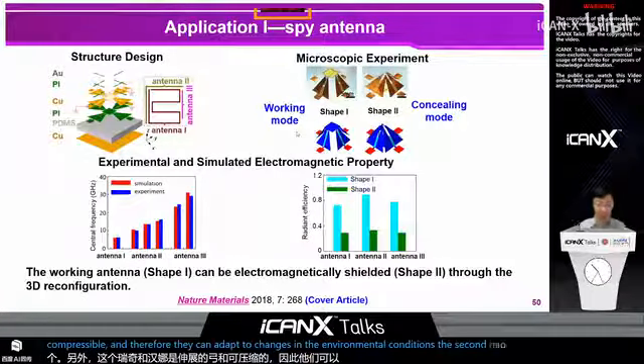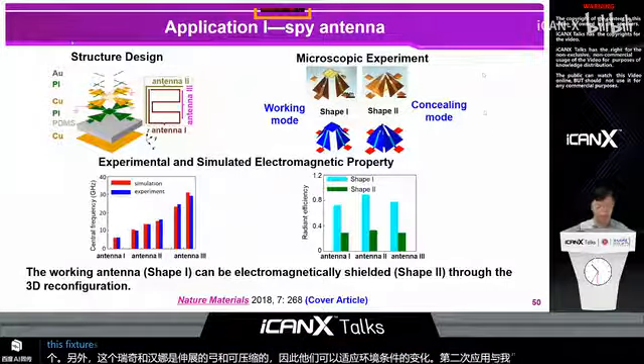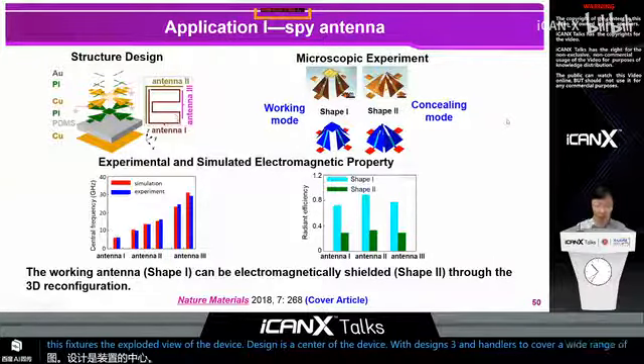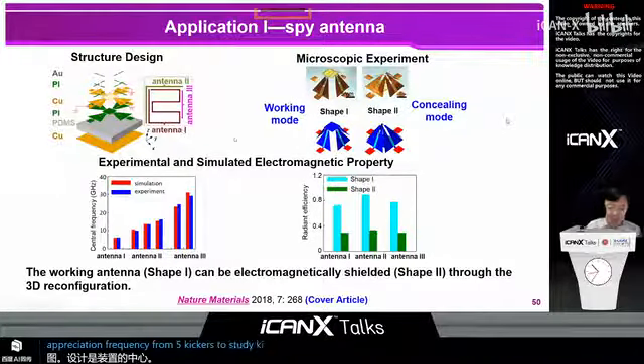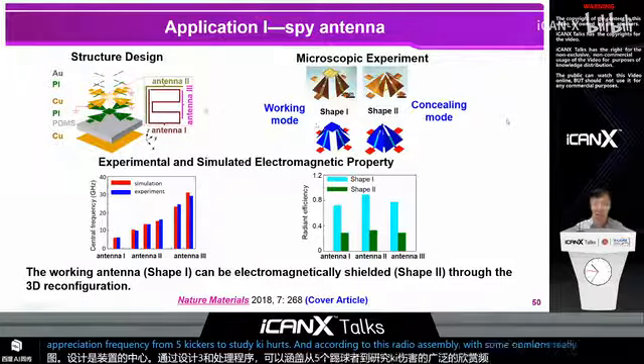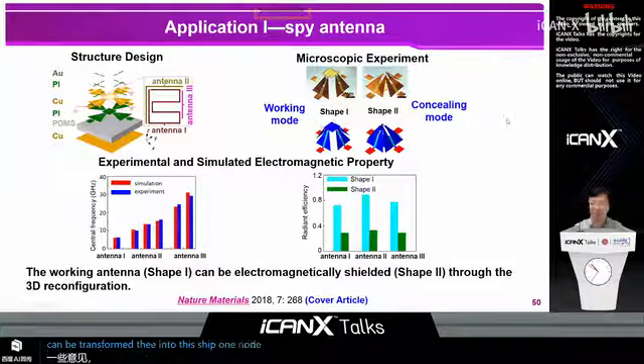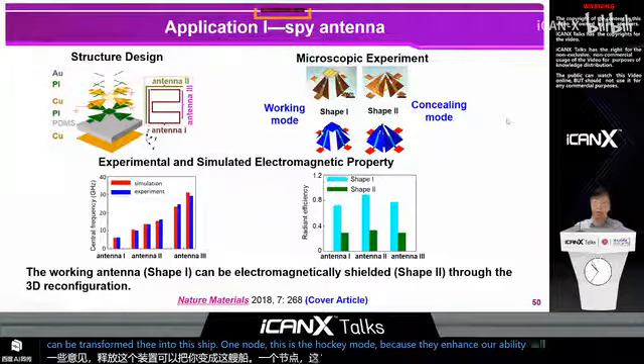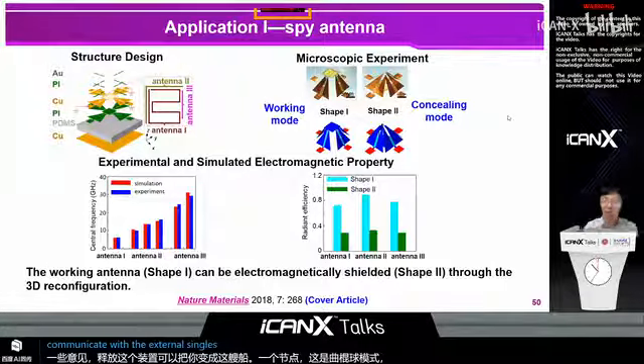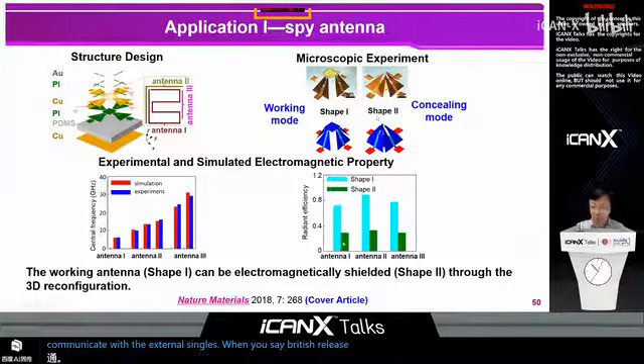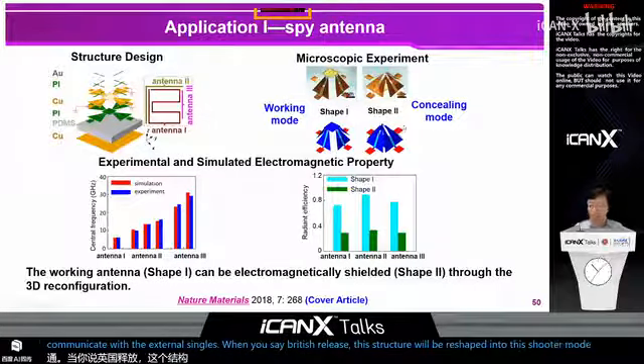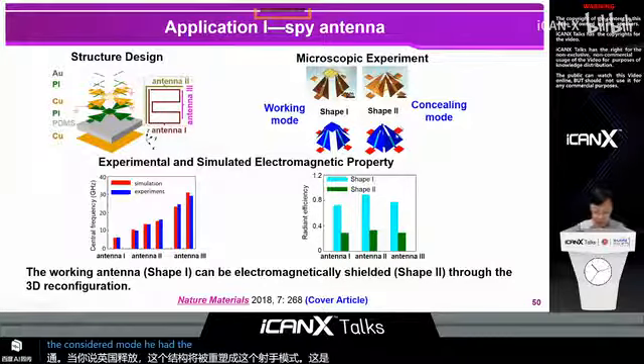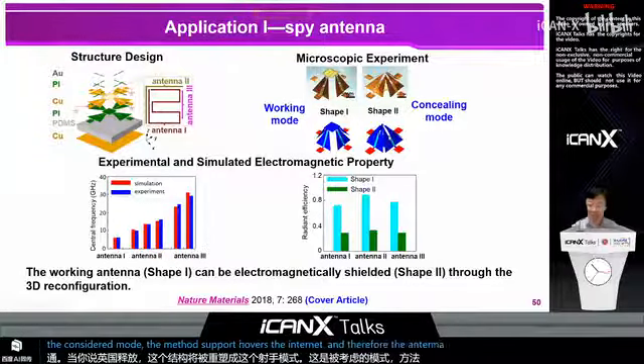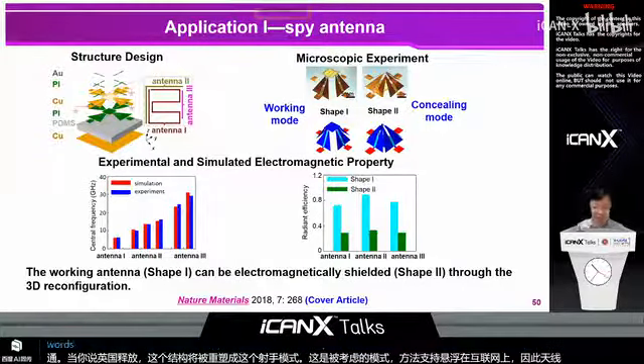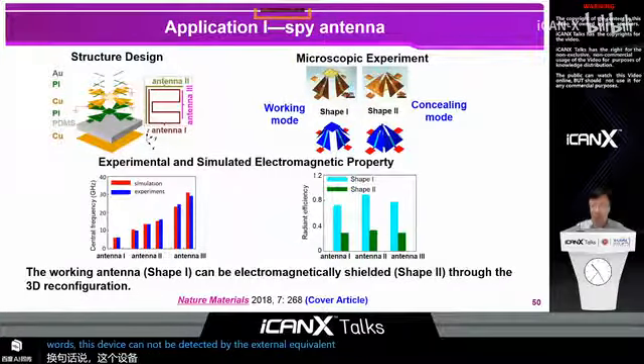The second application relates to a spy antenna. And this figure shows the exploded view of the device design. At the center of the device, we designed 3 antennas to cover a wide range of operation frequency from 5 GHz to 30 GHz. And according to 3D assembly with simultaneous release, this 2D device can be transformed into this shape 1 mode. And this is the working mode because the antennas are elevated and exposed to communicate with the external signals. But when you do sequential release, this structure will be reshaped into this shape 2 mode. And this is the concealing mode. Here, the metal support covers the antennas, and therefore the antennas are electromagnetically shielded. And in other words, this device cannot be detected by external equipment in this shape, so we call it a spy antenna.